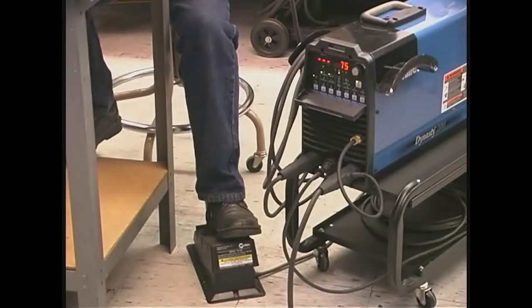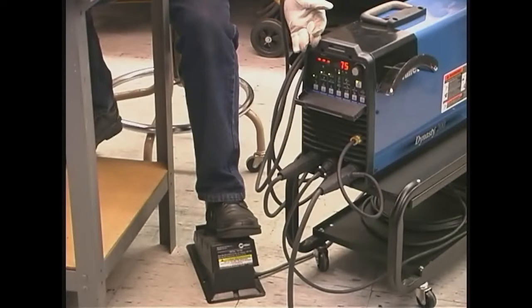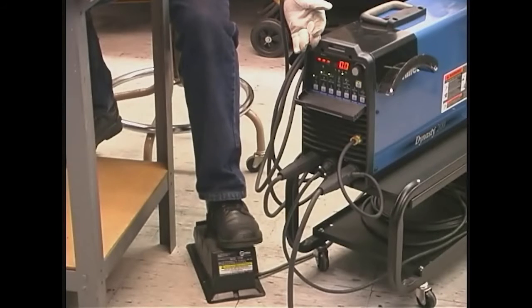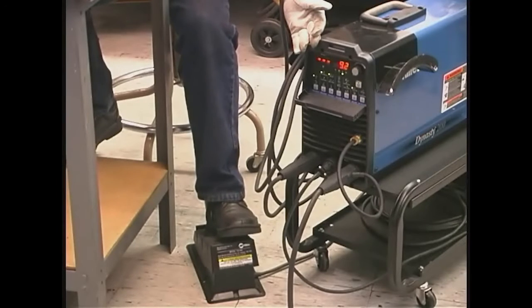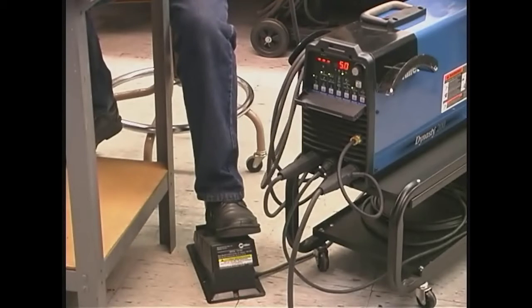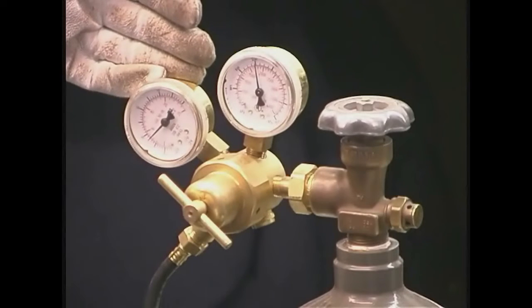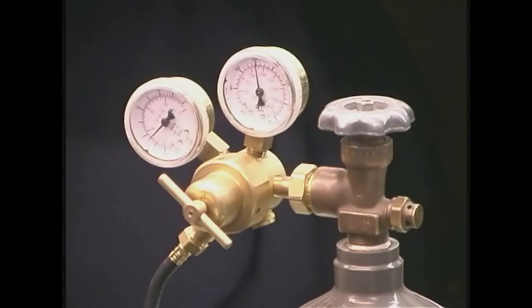Now I have the machine set up already. It's set to DC electrode negative. It's set to 75 amps. The high frequency is set to impulse start. We're using the foot control as the remote. The pulse is disabled. The sequence is disabled. And I have it set to 10 seconds of post flow and 17 cubic feet per hour of argon flow.